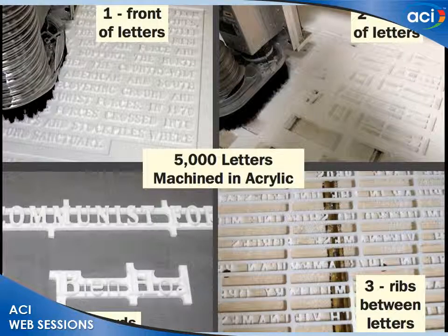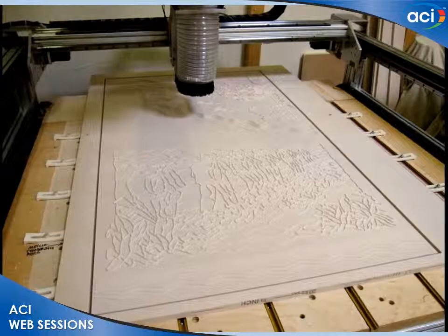For the letters, we had to match the fonts in the original map, and I believe they used those systems for the bulletin boards where they put little plastic letters in the grooves, but they had dozens of fonts back then. We only had two that we could find that we could purchase, and of course they didn't match the historic ones. So we had to find the right font, go through the typesetting and graphic process, and then machine about 5,000 letters. So we did this in a marine-grade acrylic, machined the front, machined the back, opened everything up, kept ribs, and then cut the words apart. That's the face mold being machined on the router.